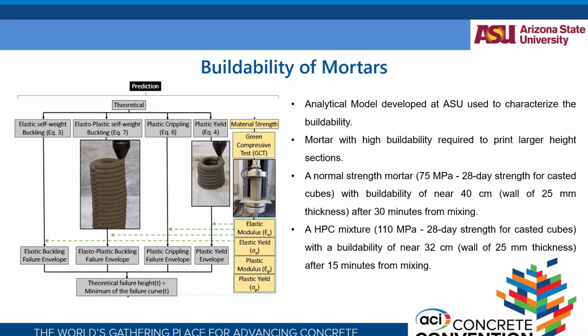One is a normal strength, higher water cement ratio mix that reaches about 75 MPa on 28-day strength. The other is a high performance concrete, basically a low water cement ratio mix, with a water cement ratio of only 0.19, and it reaches about 110 MPa, and this is without the fibers.